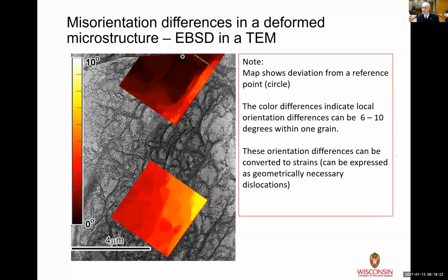And today you actually have systems that you can put inside your electron microscope that allow you to make EBSD maps using the probe of the electron beam. So now you're talking about a beam size that's much smaller than you'll get in an SEM, even in your best SEM. It's much smaller. And you can actually start pinpointing where the stress is coming from. You can actually measure it. So the two color-coded squares that you see here are just two areas of a grain. And we've gone in and we've measured the misorientation. And you can see the difference.